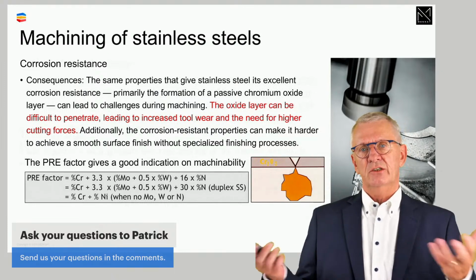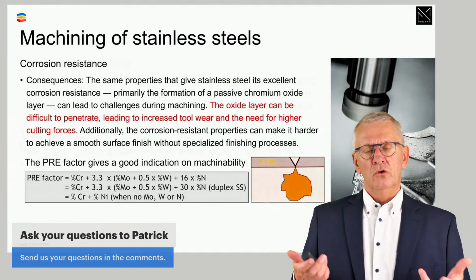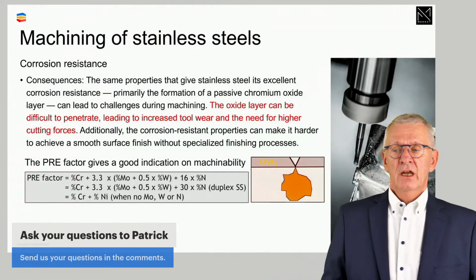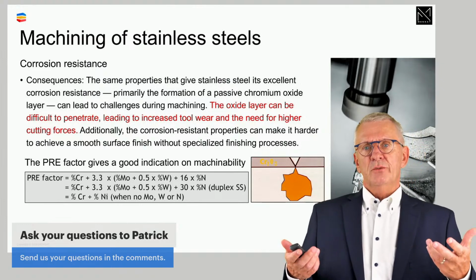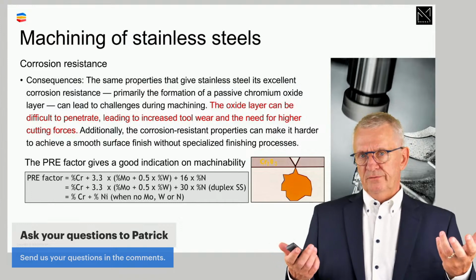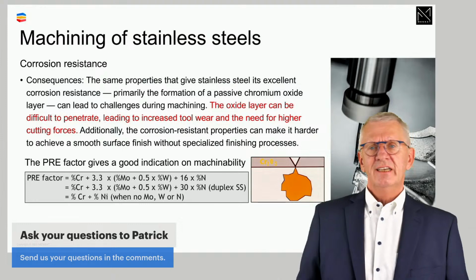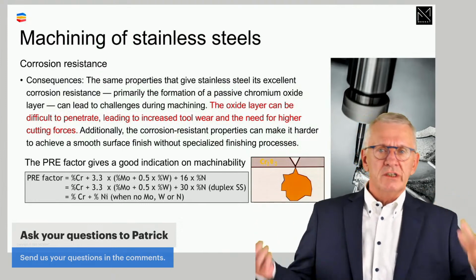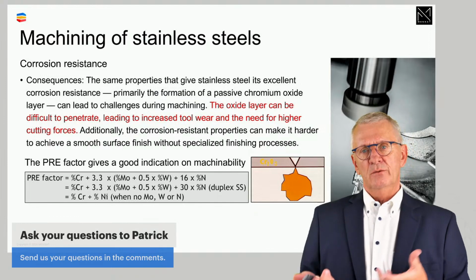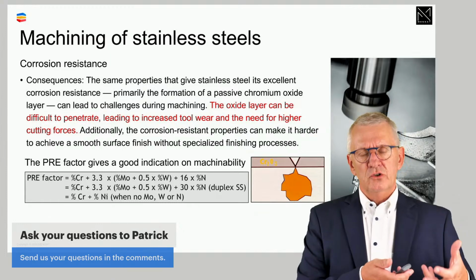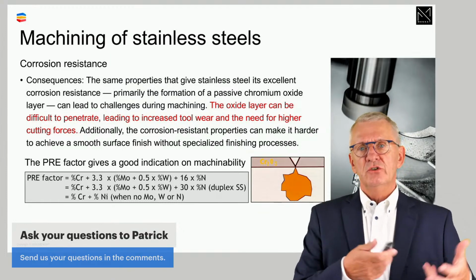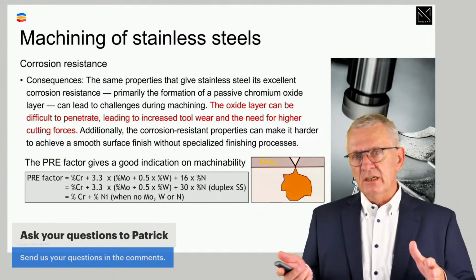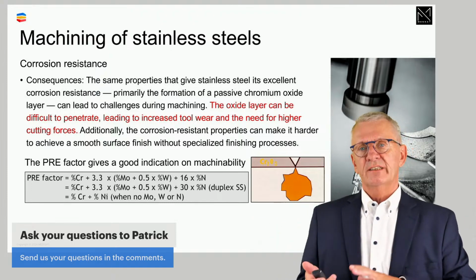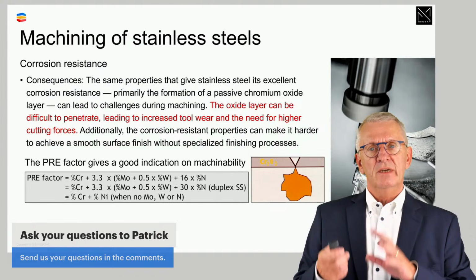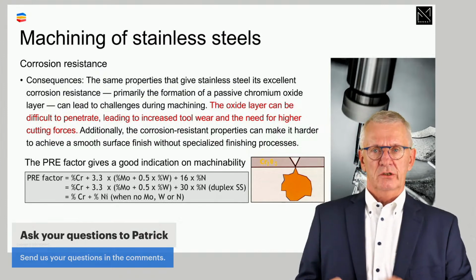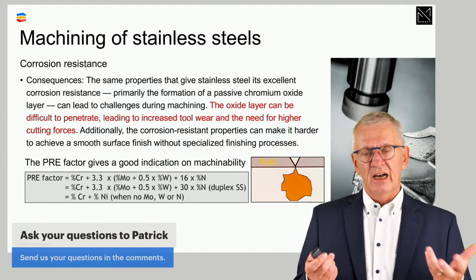Corrosion resistance, as I said, and here just for sentimental reasons, I bring that corrosion or anti-corrosion layer again on the table. People say, okay, if you know the PRE factor, and the PRE is a factor which we use for defining kind of the quality of a stainless steel, the higher the PRE, the higher the corrosion resistance is, one could say. But if you have a high PRE, it means that you have a strongly formed anti-corrosion chromium oxide layer, and if we have to machine through that, it has consequences. 40 years ago, we thought that was it. Today, we know better. We know that this plays a role, but much more important is the formation of a strain-hardened layer on a machined surface that influences how the process goes.